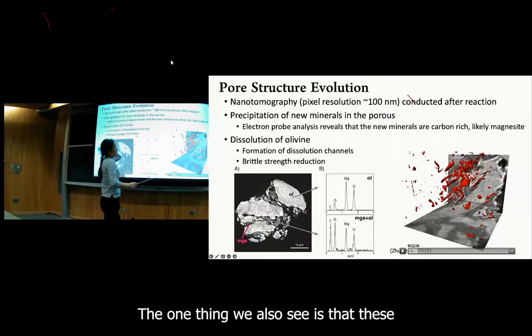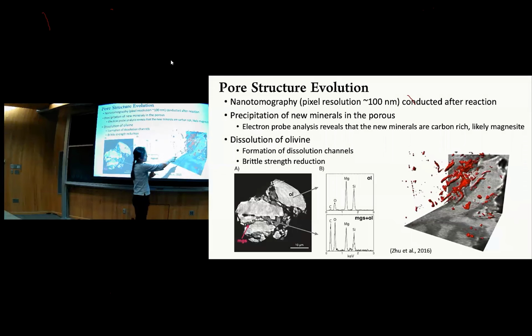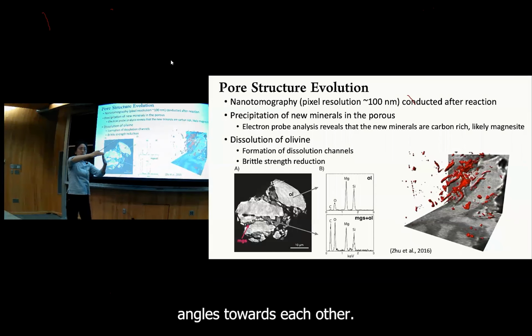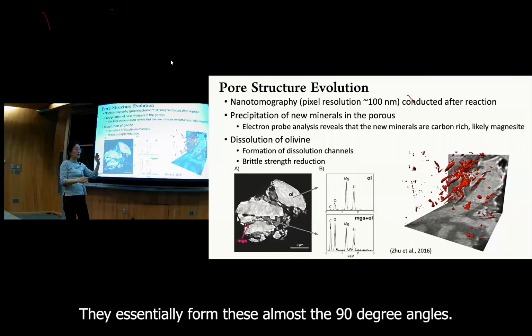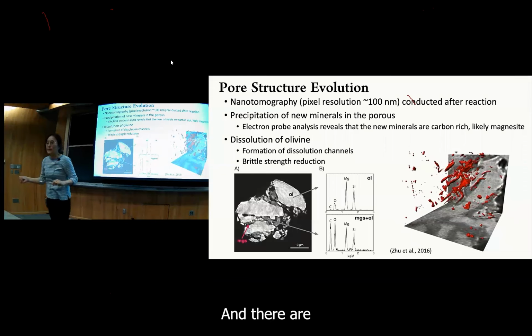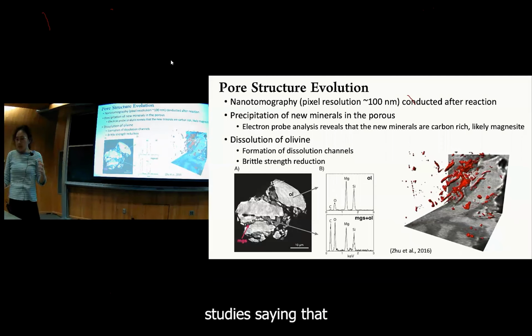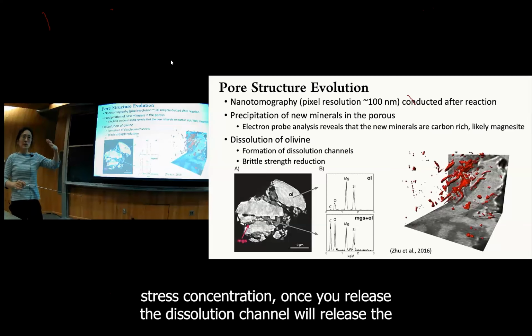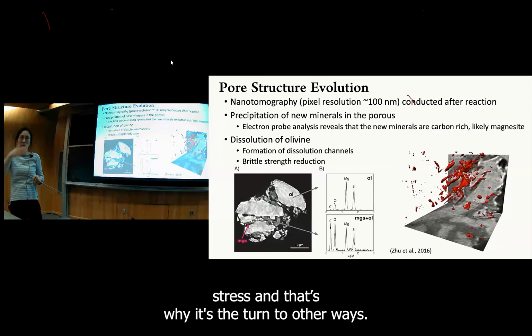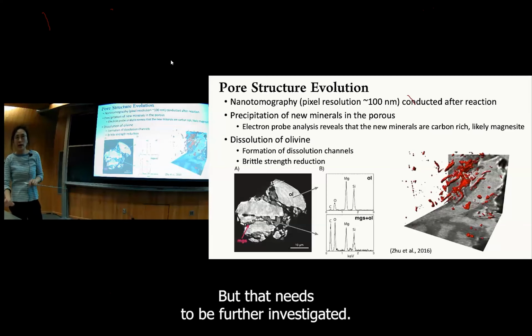The one thing we also see is that these voids actually have these angles towards each other. They essentially form these almost 90-degree angles. And there are studies saying that this could be an indication of stress concentration. Once you release the dissolution channel, it will release the stress, and that's why it turns the other ways. But that needs to be further investigated.